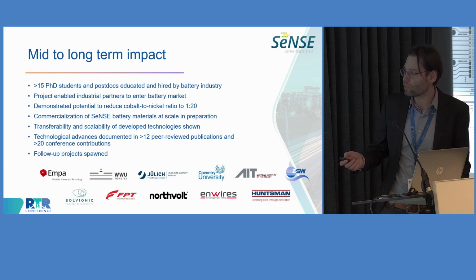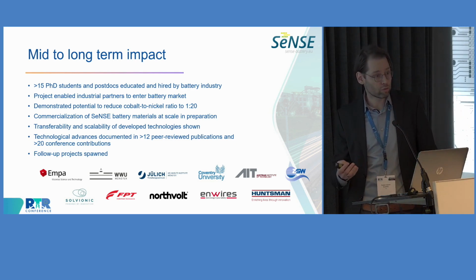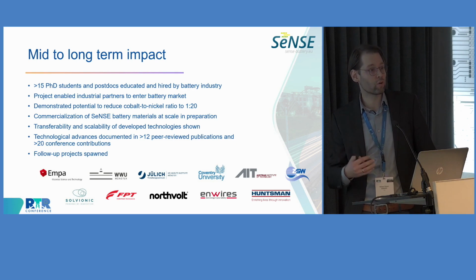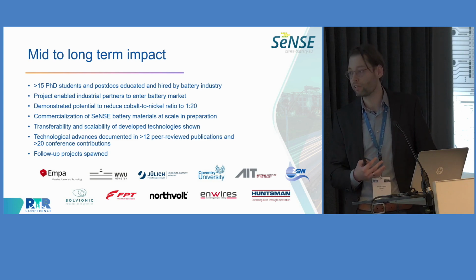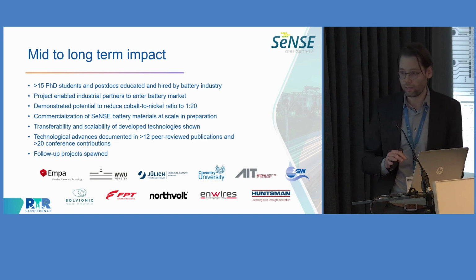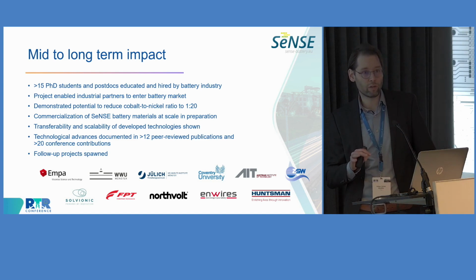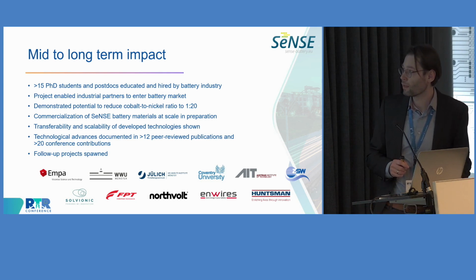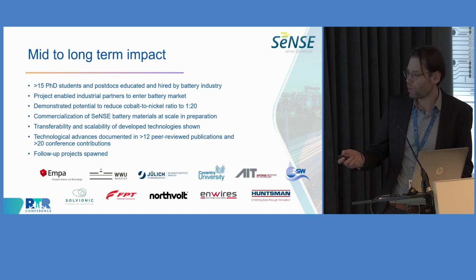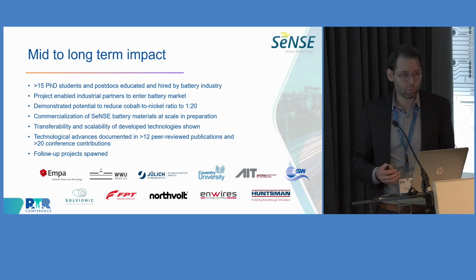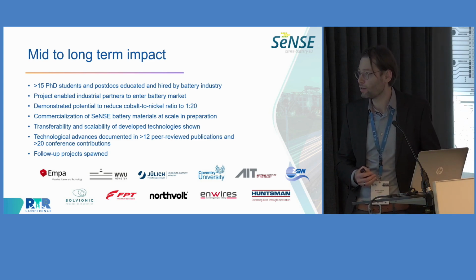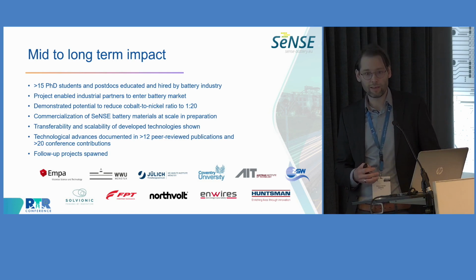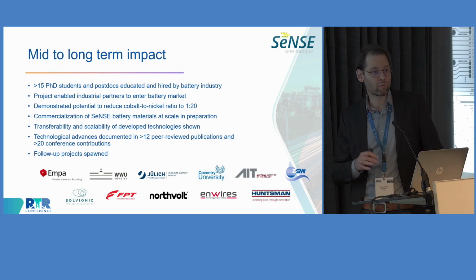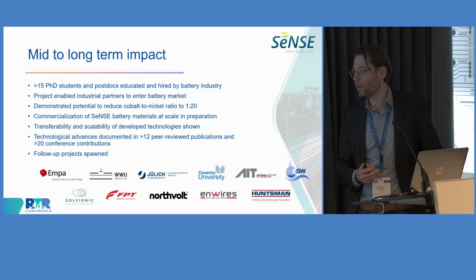Really a highlight for us was my first highlight to show that it's possible to reduce the cobalt content significantly in these nickel-rich NMC materials while maintaining a good cycling stability. This goes into the environmental factor and into Europe's dependence from critical raw materials. And yeah, I already mentioned that we have this follow-up project. I think further follow-up projects are in the pipeline. And we also have partners that are really close to commercializing technology that we've been developing here in the project at a relevant scale. So that's also really nice.